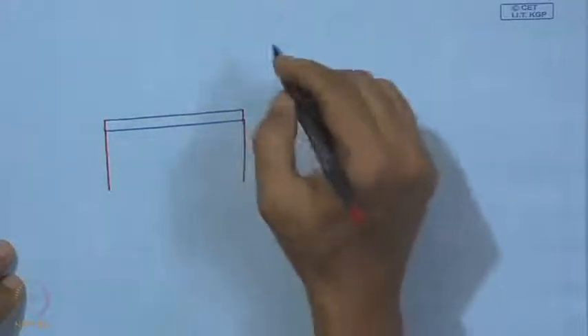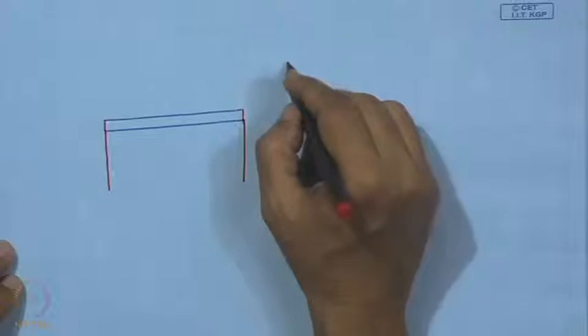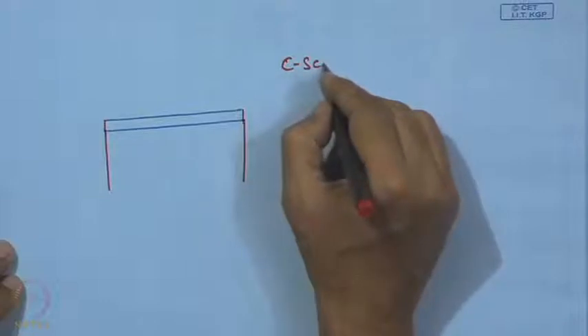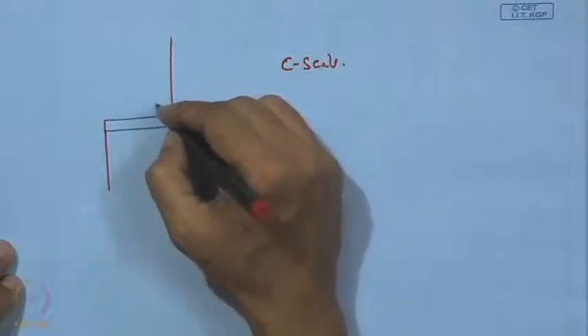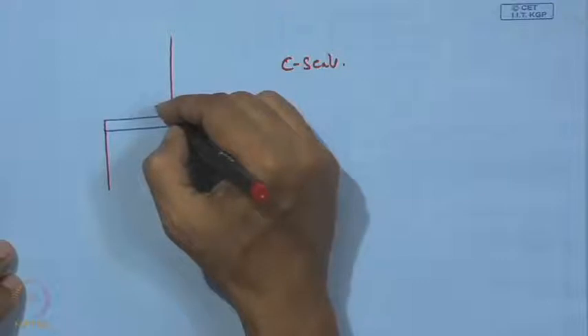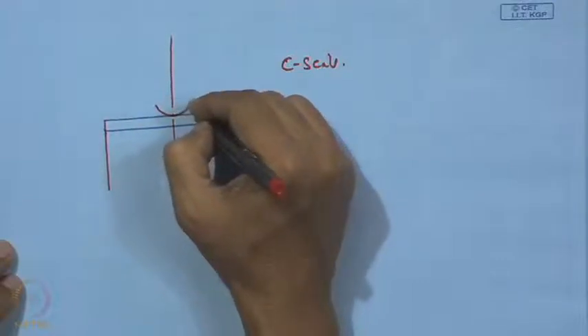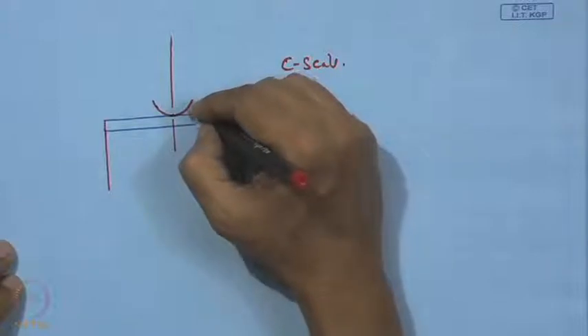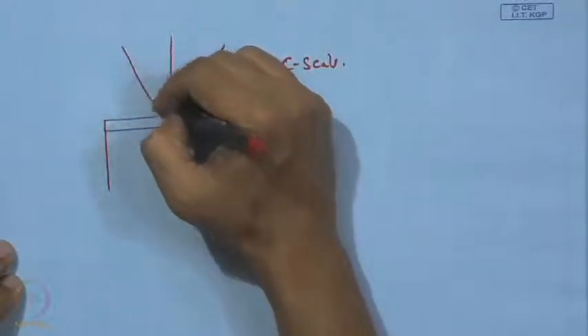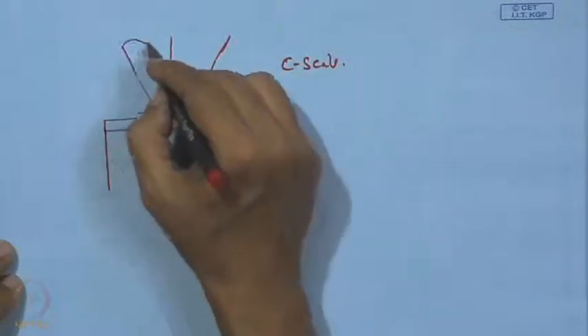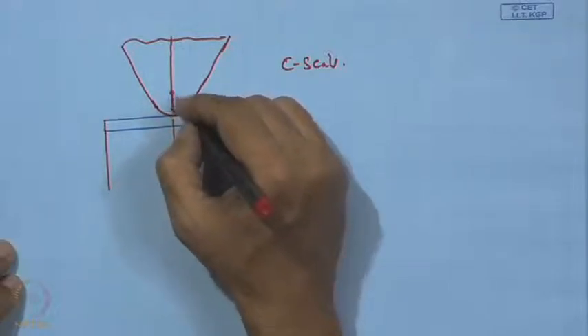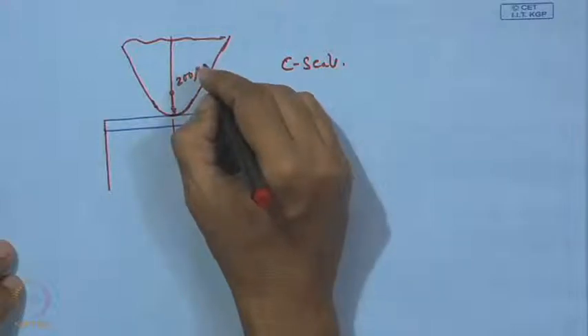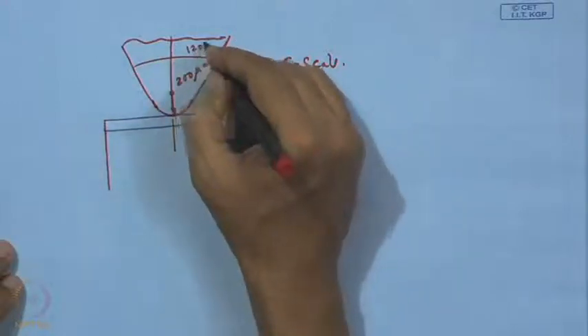Depending on the cracked area, an attempt is made to assess the coating-substrate interface. The indenter used is a Rockwell C scale diamond brale — a cone of diamond with a hemispherical tip, a cone angle of 120 degrees, and a tip radius of 200 microns. This is the same well-known indenter used routinely for hardness measurement.